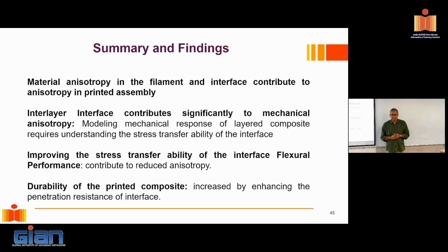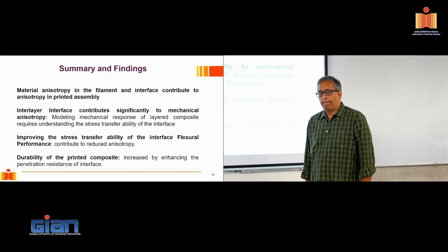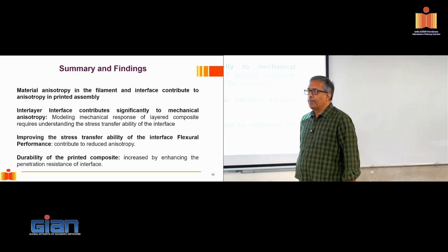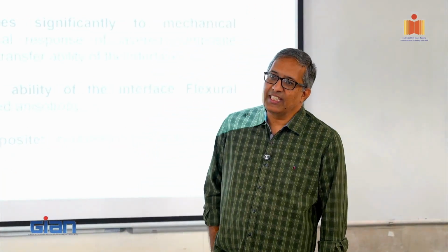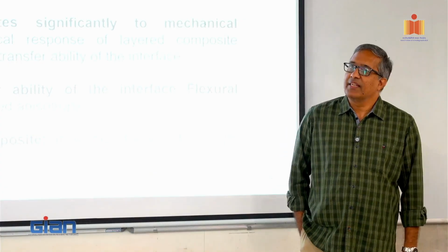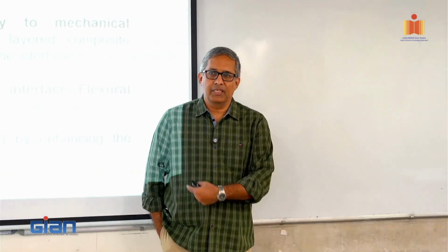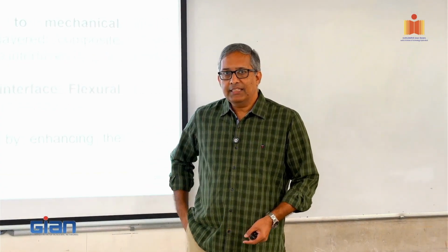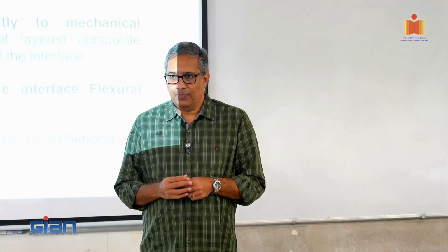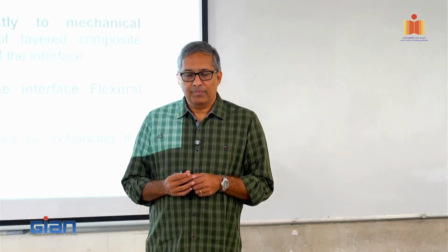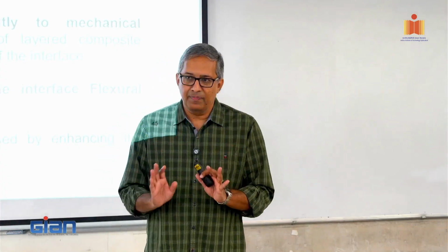Is anisotropy also time dependent? Yes. That means if you are having some durability issues, will the anisotropic factor increase? Absolutely. So it should, just the same way as it would in concrete. Even concrete is a chemomechanical material. So when you have degradation, it affects its performance. Very similar, except here the degradation will happen preferentially at the interface. That's my weak link, right? So absolutely the same set of mechanics.